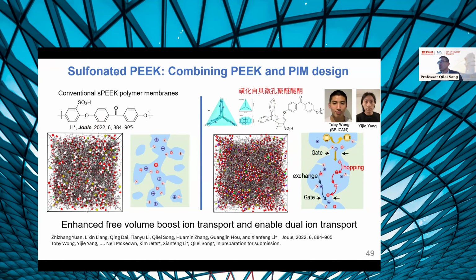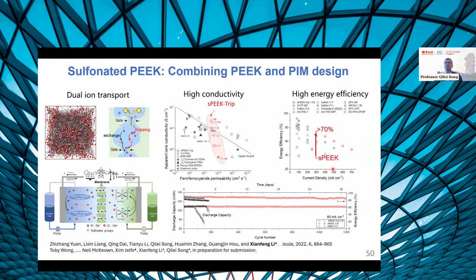You can see that you got ion exchange and ion hopping through these functional groups. So this kind of dual ion transport is very useful. Especially in the alkaline electrolyte, we were able to get very high energy efficiency and retain the selectivity towards the redox species. And when you integrate this membrane into the battery, you got significant improvement. You can see that our new membranes give much higher energy efficiency, and the battery can be operated at very high current density. And to the best of our knowledge, this is the highest to date.